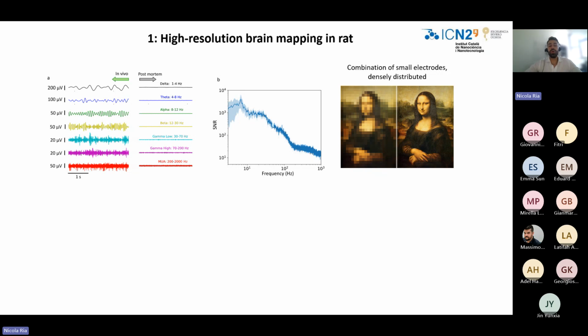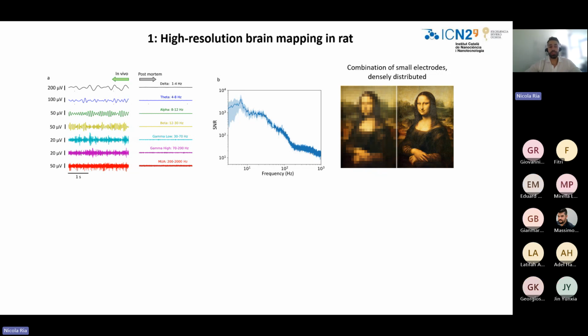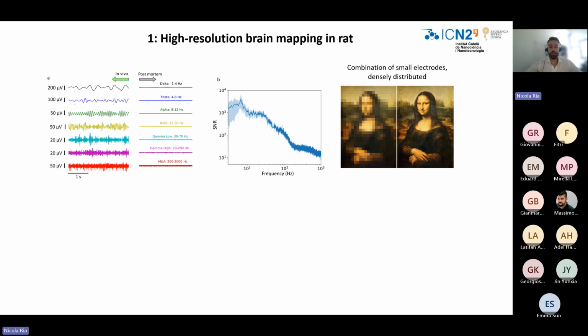So post-mortem, we have a baseline that is just noise, while in vivo you can appreciate from a qualitative point of view that there is much more activity, so there is biological content, that is the real signal that we want to measure. To quantify this difference, we also plot the signal-to-noise ratio that shows values above 10 for the whole frequency range.